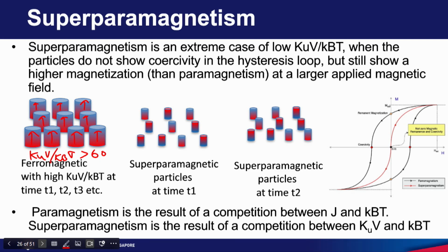On the other hand, if I make the particle small, let us say I initially magnetize along this direction, but after I remove the magnetic field, some of them would be in the other direction. So you observe these particles keep fluctuating as a function of time, like the animation that I showed you. Because of that reason, these materials do not have a hysteresis. Superparamagnetic materials do not have a coercivity, but they do have a large magnetization, because these are still ferromagnetic particles. Within these particles, the spins are still parallel to each other.